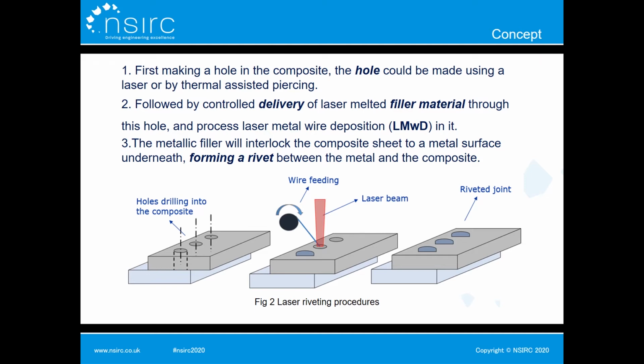Therefore, according to this concept, there are 2 key points. First is the laser wire deposition on the metal substrate, and another is the interaction between the melt wire and the interface of the hole in the composite sheet. Because I am a second-year student, before working with composite directly, I want to investigate the laser wire deposition processing systematically. So last year, my work focused only on the study of laser wire deposition on the metal substrate. In this presentation, I will introduce my results step by step, from feasibility study to parameter improvements and further experiment trials.